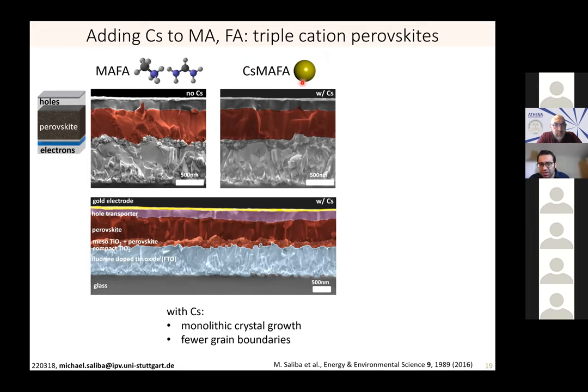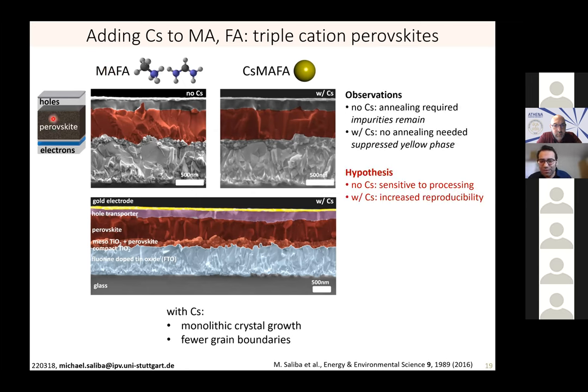So this was the idea of a new design principle. Can a small quantity of cesium improve MAFA? And of course, I put it very suggestively. The answer is yes. What we observed was that without cesium, these methylammonium formamidinium perovskites require annealing. They have impurities on the X-ray, which we show in this paper here. And with cesium, all of a sudden, these small yellow phase impurities visible on the X-ray disappear. But this gives a bigger hypothesis that the presence of cesium makes the perovskite formation less sensitive.